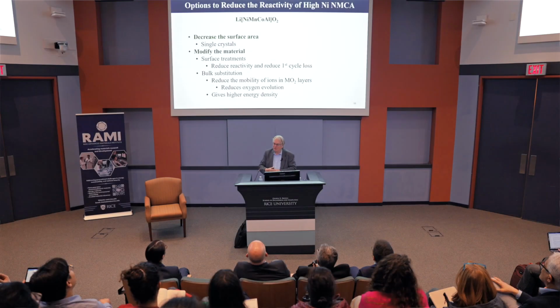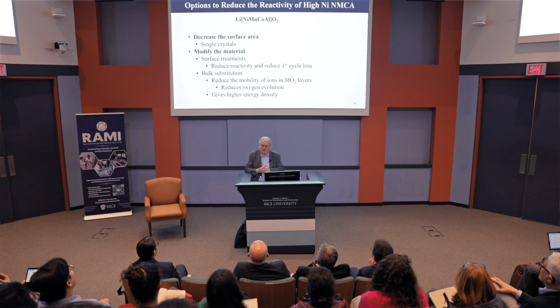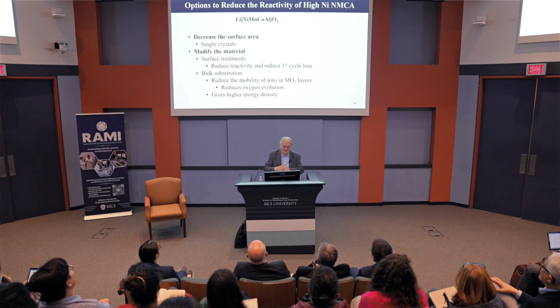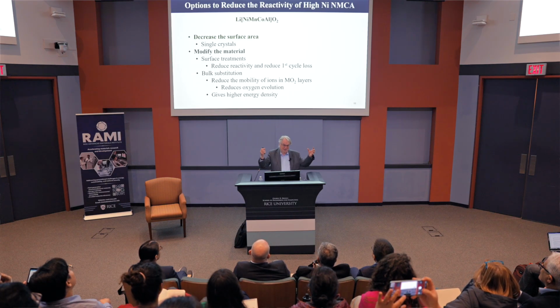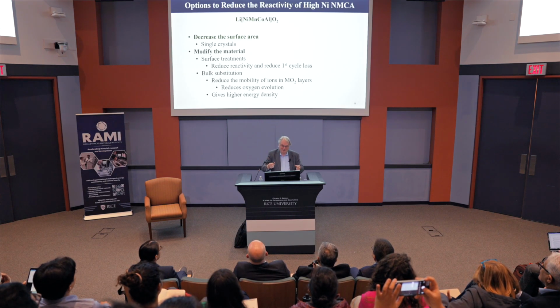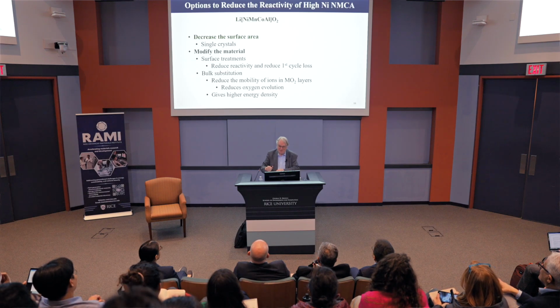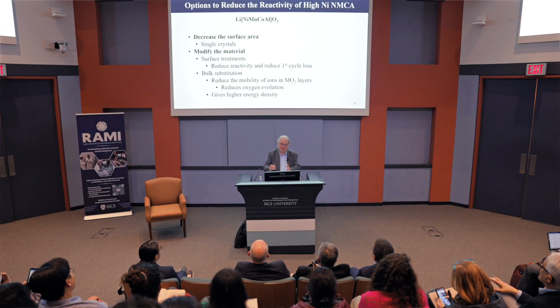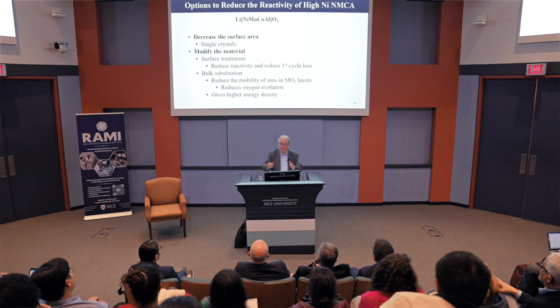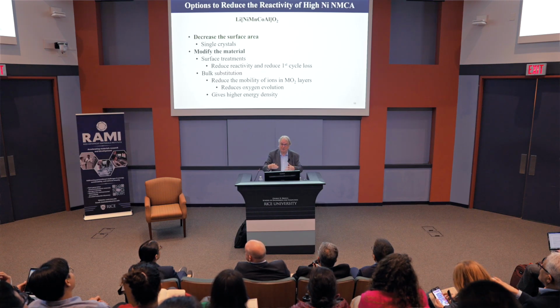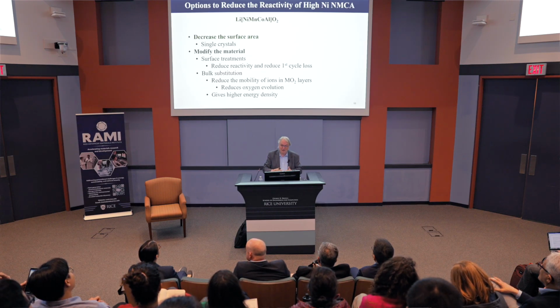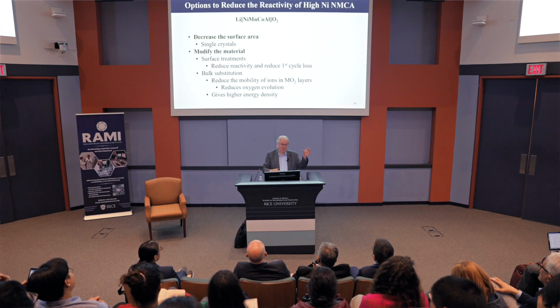So how do we reduce the reactivity of these materials? Well, there's some obvious ways. Reduce the surface area. So any of you doing catalysis, you want lots of surface area to catalyze the reaction. Well, we don't want to catalyze the reaction with the electrolyte, so we want less and less surface area. You reduce the surface area, you reduce the current and the power, so there's a negative there. So we can go to less surface area, means go to single crystals rather than meatballs,